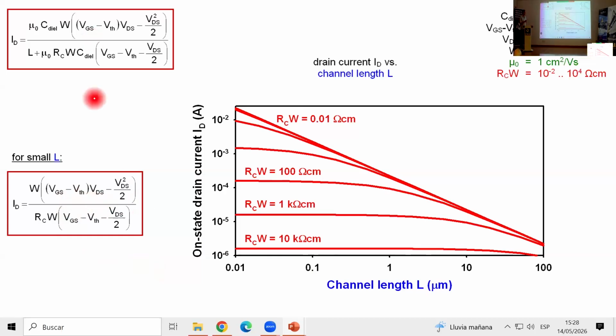And we see that here: if the channel length becomes really small, then this equation can be simplified to this equation. And it turns out that now the drain current is independent of channel length. And this is basically what we see here, right? We see a saturation here. So for large contact resistances, there's going to be a saturation in terms of drain current. So minimizing the channel length below a certain value will no longer result in an improvement in on-state drain current, except if we find ways to minimize the contact resistance. In that case, any reduction in channel length will give us an improvement in on-state drain current.